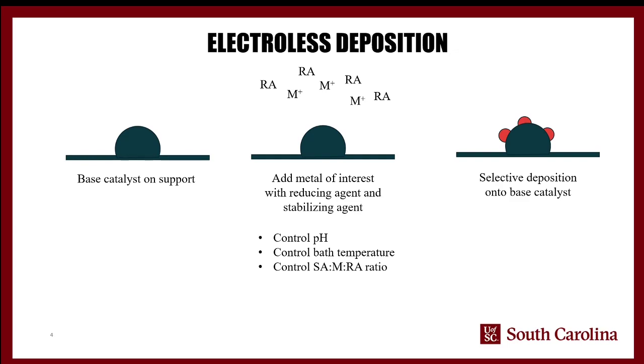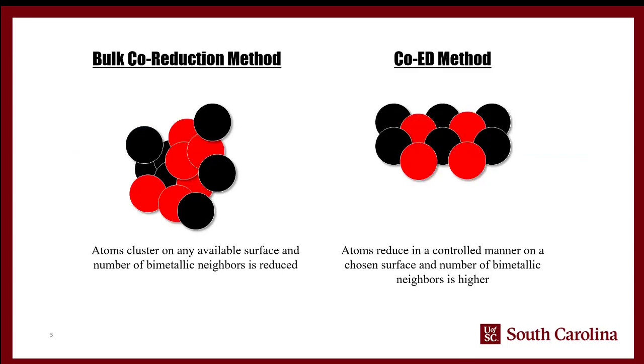And so finally, by controlling all these, you get your selective deposition onto the base catalyst, and that's the goal. So as I talked about, you've got your bulk co-reduction method here on the left. You might end up with a bimetallic particle, but your nearest neighbor is not necessarily going to be of a true bimetallic nature. So you will have some regions that are platinum rich, for instance, and some regions that are ruthenium rich. You might have some platinum and ruthenium neighbors, but it won't be an optimal mixing to where you're maximizing your active area. On the other hand, with the co-electroless deposition method, you're going to get atoms reducing in a very controlled manner. And by controlling the ratios and the environmental conditions, you're going to end up with more atoms with bimetallic neighbors than you would in a bulk reduction method.